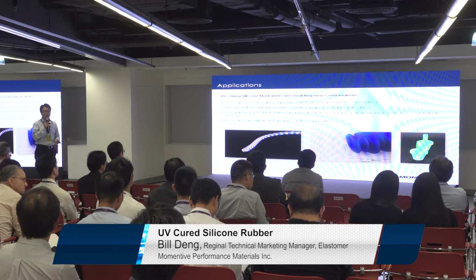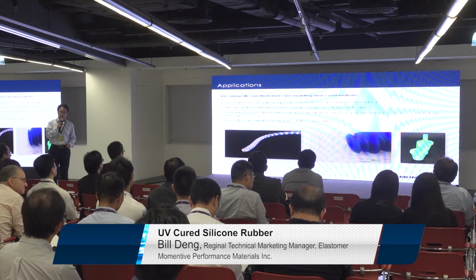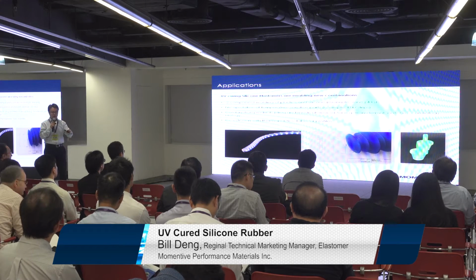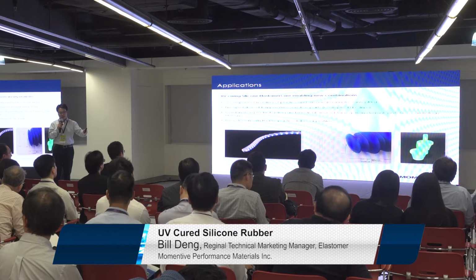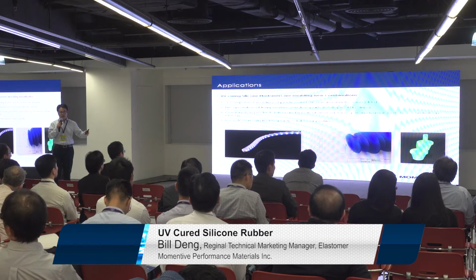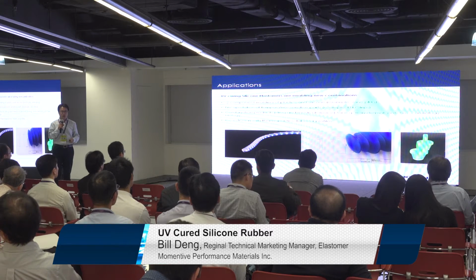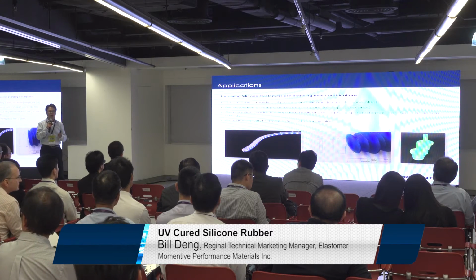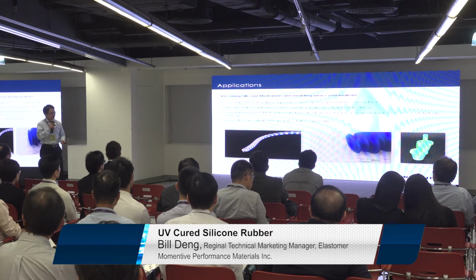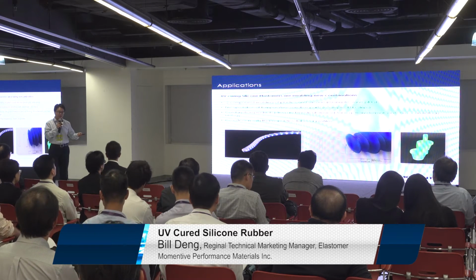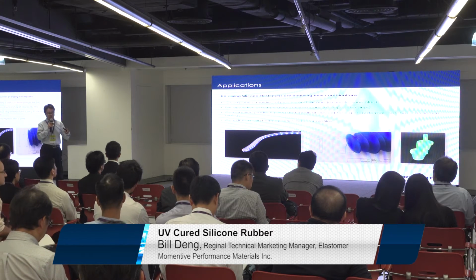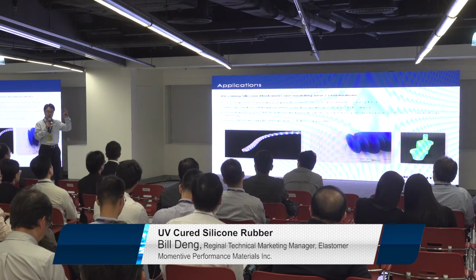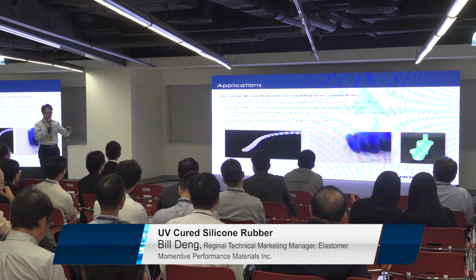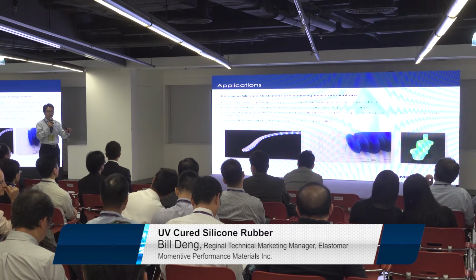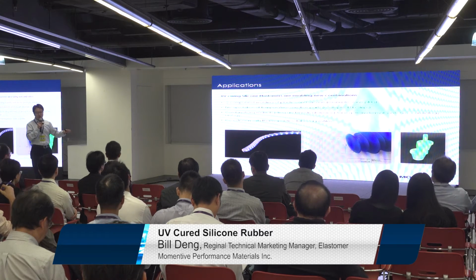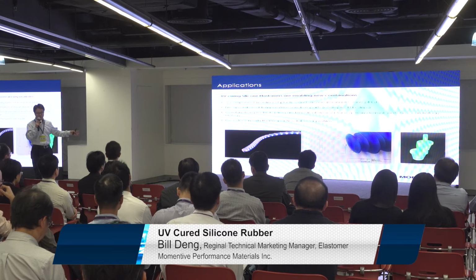So the traditional way is not to use an injection molding machine. They will mix the A and B parts, like from 2 drums, and go into a big mold. There is steam surrounding the mold. So the curing time will be long, can be 1 day, 24 hours to make the part. But if we use UV cured technology, we mix A and B, the catalyst and the base, and put it into the mold, then just use the light to catalyze the material. Then it requires maybe just a few hours for the big part.